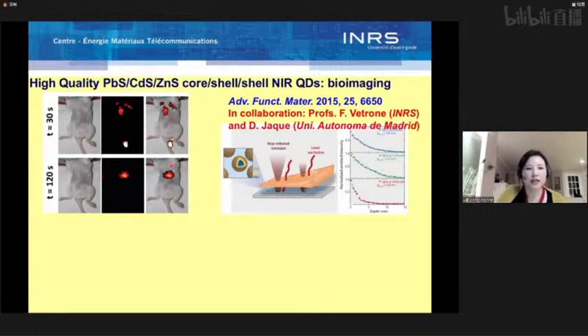So here shows that we can use these quantum dots to follow the distribution of quantum dots inside the mice. And we did deep tissue imaging. We can find quantum dots in microchannels. We put chicken tissue of different thickness on top, and we use near-infrared light to excite quantum dots, and then we measure infrared emission with the camera.